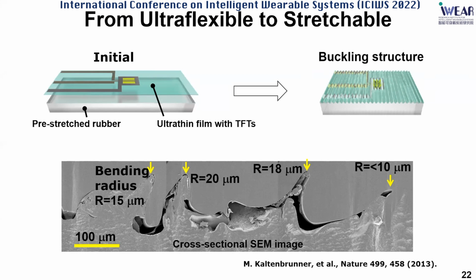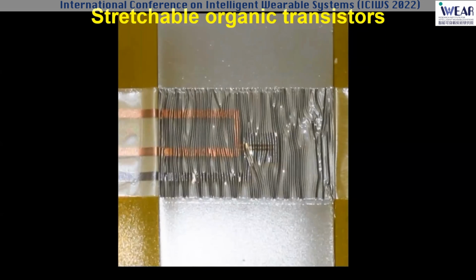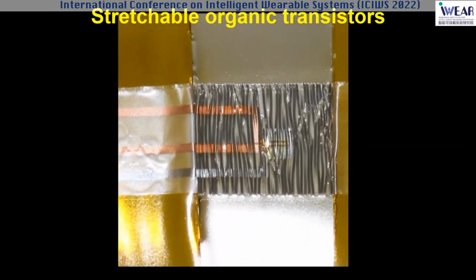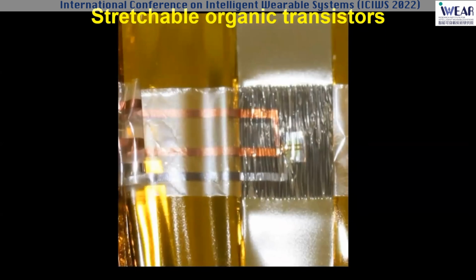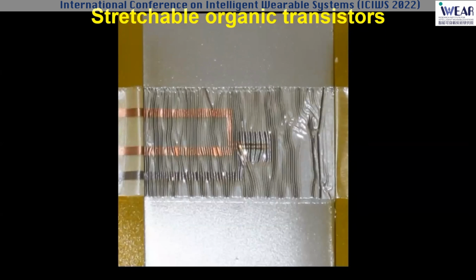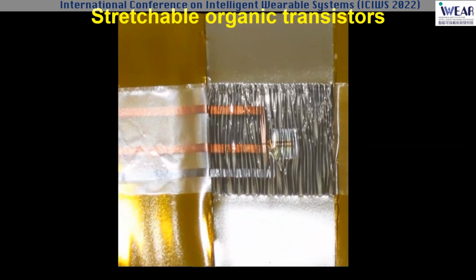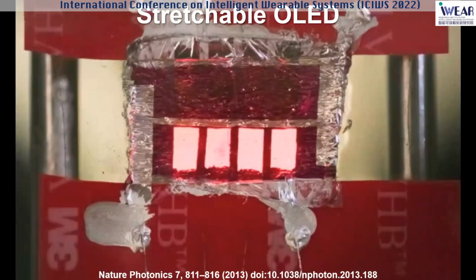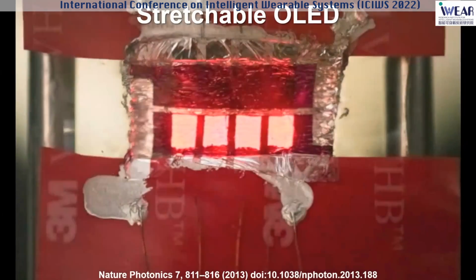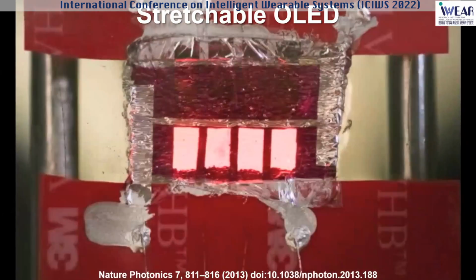And if we look at the bending area very carefully, the bending radius may change from 10, 18, 20, or 15 micron. But our device doesn't cause any mechanical failure, even though that was bent at the sharp bending radius of 5 to 10 micron. And so in this way, we can easily transform the ultra-thin film devices to be stretchable like this. So this is the original length and start shrinking and coming back to the original length. And we can make the other semiconductor devices to be stretchable.